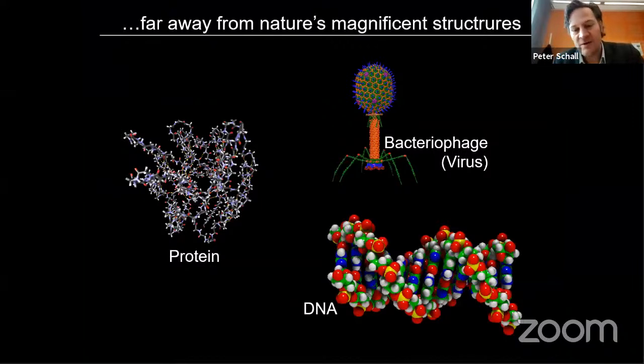And of course, there are several reasons for that. One reason is, of course, that it is still hard to get equilibrium phases, so to control the interactions in a way that they're of the order of a kT or two, or maybe half a kT, and adjustable, so that you can actually let the system evolve in a true equilibrium manner. Another reason, of course, is that the complexity of these structures goes down to essentially the complexity of the quantum mechanical states of the atoms and molecules, especially carbon with its different hybridization states, etc., which are difficult to mimic. For all these reasons, of course, we realize that with colloids we are far away, but we're making progress. We're making some steps.